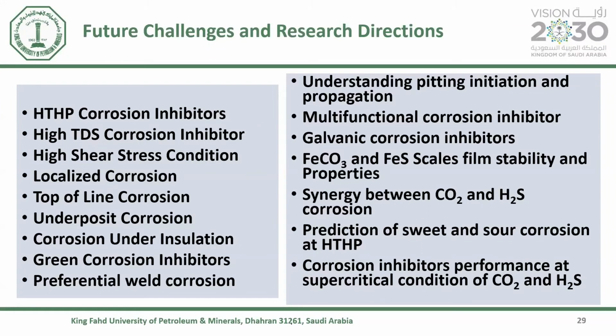There are still a lot of problems with corrosion for downhole wells at high temperature and pressure, and this also poses challenges for corrosion inhibitors. For high TDS, total dissolved solids, some of the brine can go up to 250,000 ppm. This is very high, so it will also pose a challenge. High shear stress conditions. Localized corrosion is very important because normally the general corrosion rate is not really a problem, but localized corrosion is a serious problem. We also have top of the line corrosion.